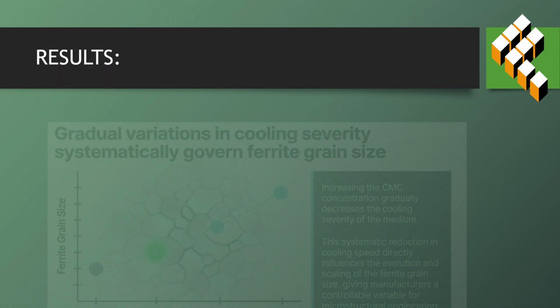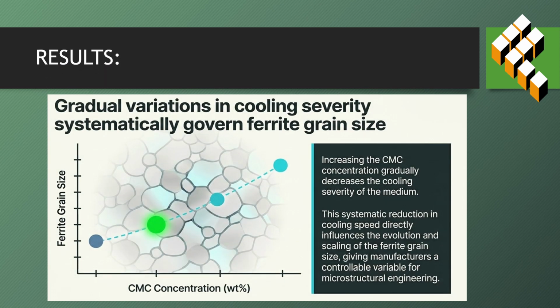Results. Gradual variations in cooling severity systematically govern ferrite grain size. Increasing the CMC concentration gradually decreases the cooling severity of the medium. This systematic reduction in cooling speed directly influences the evolution and scaling of the ferrite grain size, giving manufacturers a controllable variable for microstructural engineering.